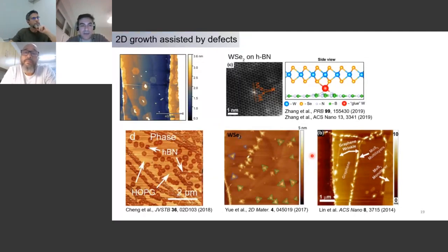Basically, then you can be quite relaxed in that respect, because of course you can use one sample for many types of characterization, but you could also say I grow 2-3 samples for different methods, and they are quite reproducible. That's the nice thing about MBE. Once your template is reproducible, in this case epitaxial graphene on silicon carbide, the parameters in the MBE are also very reproducible. That's the nice thing.